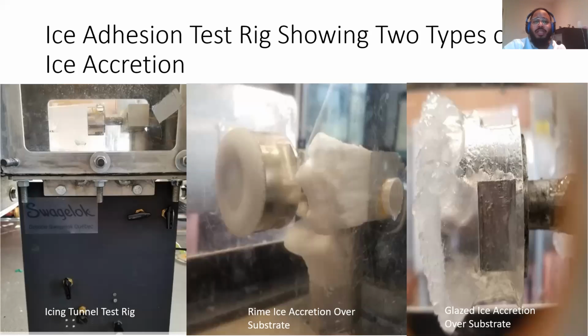The crack develops through the application of an external pressure, or in this case, what we used was an air pressure. The stress considered will be the maximum principal stress for tensile tests. The project will look to understand the effect of the type of ice formed on different substrates through mimicking of an icing wind tunnel that was designed by the 2017 Capstone Group. This wind tunnel replicated flight ice conditions and the effect of ice accretion on the aircrafts. The icing conditions were on an aluminum sample and a never wet treatment, which is essentially a super hydrophobic coating, with the pressure applied to the ice.